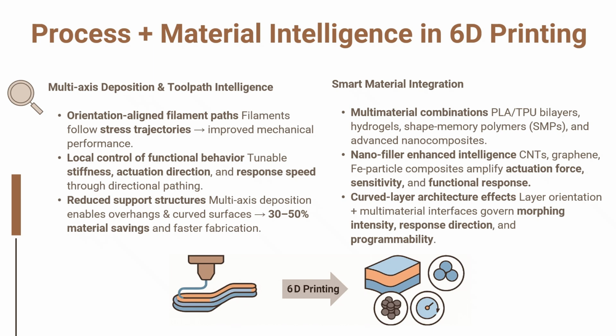On the material side, we integrate smart materials such as PLA-TPU layers, hydrogels, shape memory polymers, and advanced nanocomposites. Nanofillers such as carbon nanotubes, graphene, or iron particle systems amplify the actuation force, sensitivity, and overall functional response of the printed part. When we combine these materials with curved layer deposition, the interface geometry governs how the structure morphs. The intensity of bending, the direction of actuation, and the degree of programmability become controllable design parameters.